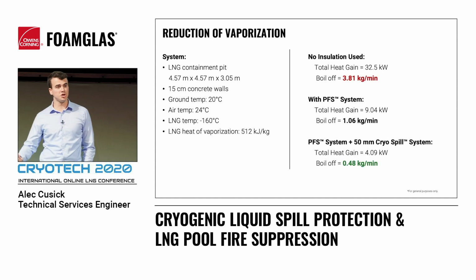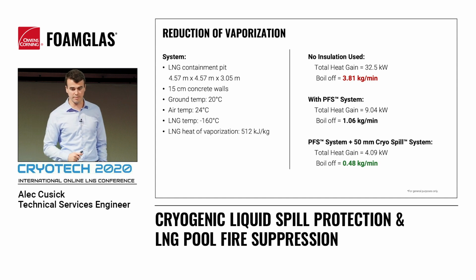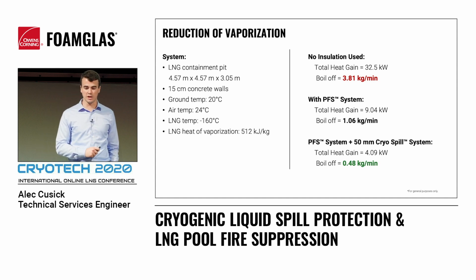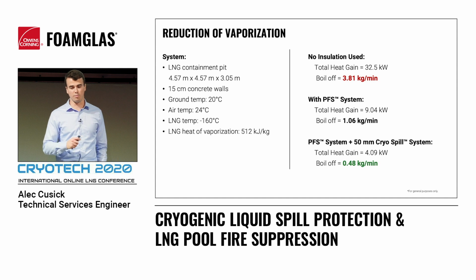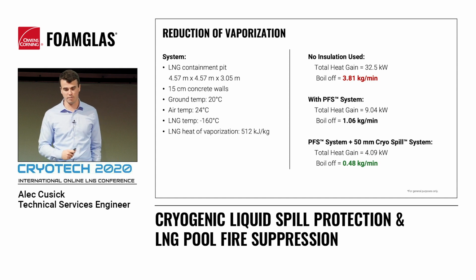Now, with no insulation used, no protection system installed, the total heat gain into the system is about 32.5 kilowatts, equating to a boil-off of around 3.8 kilograms per minute of LNG. Just by installing our PFS system, that total heat gain can be reduced to 9 kilowatts, equating to a boil-off of just over 1 kilogram per minute.